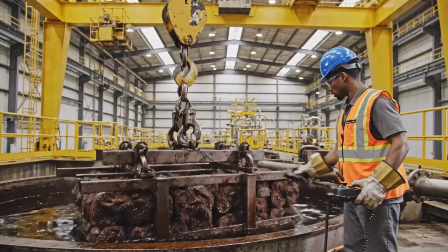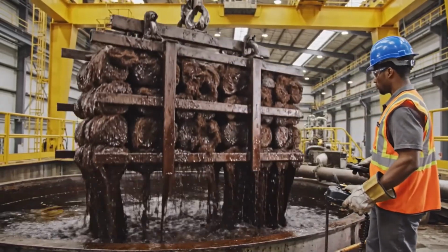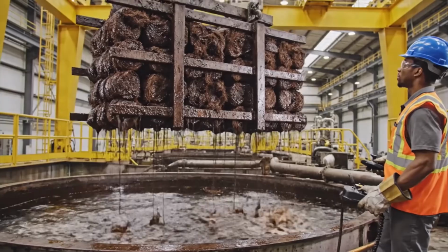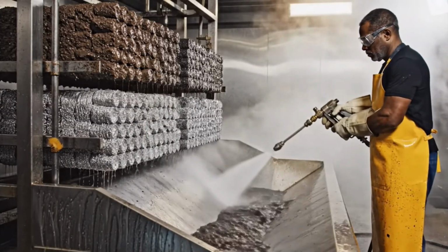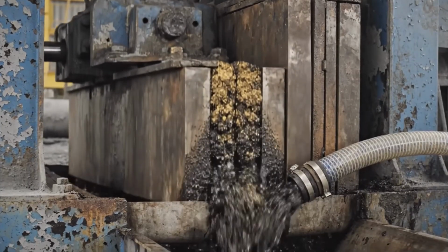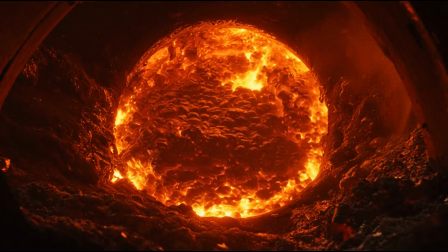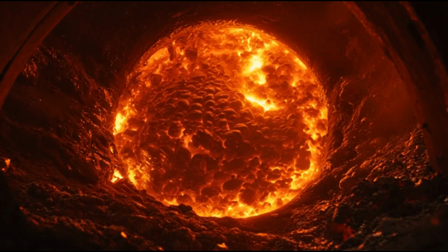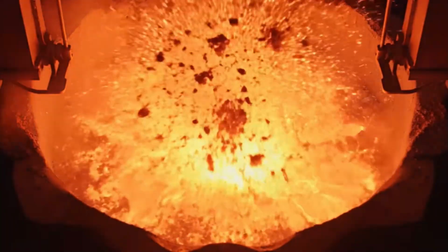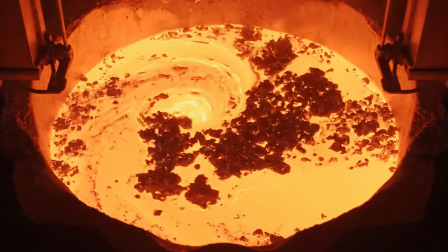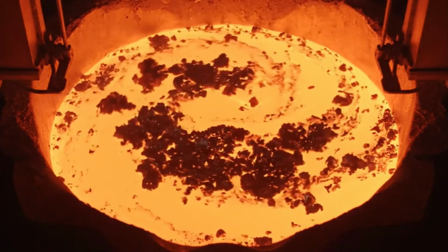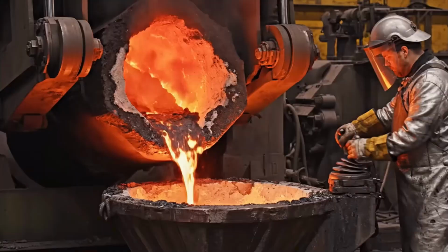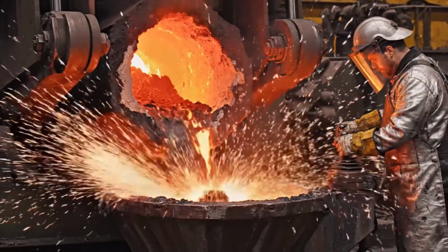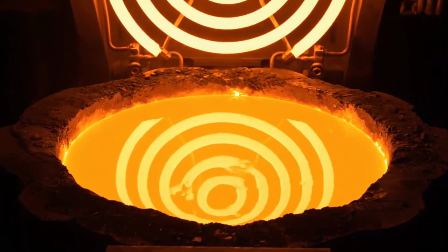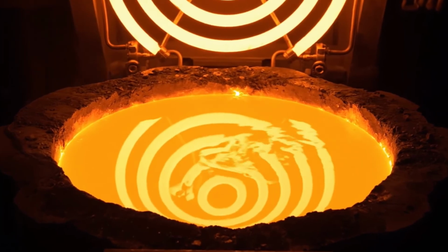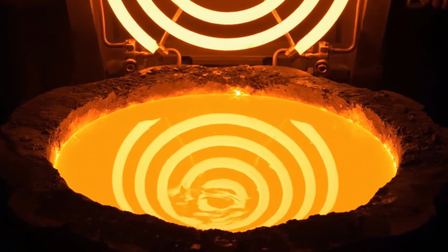The doré heads to a refinery, either on-site or a dedicated facility, to push its purity as near to 100% as achievable. The standard modern method combines the Miller chlorination process with electrolytic refining. During the Miller process, chlorine gas gets bubbled through the molten doré. The chlorine reacts with silver and other base metals, turning them into chlorides that rise to the top as slag and get skimmed away. This raises purity to about 99.5%. Impressive, but still short of investment-grade quality.